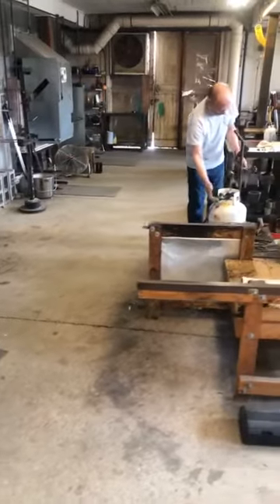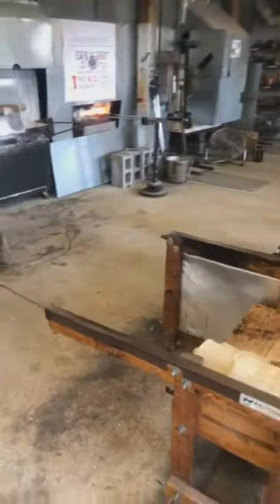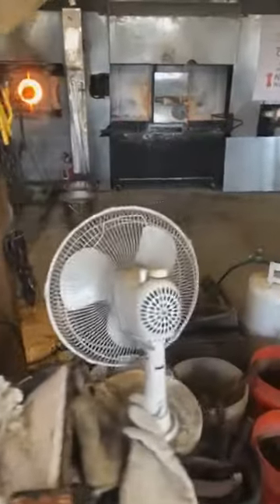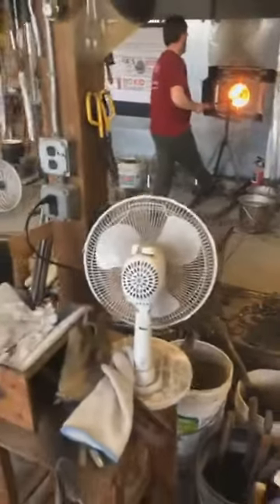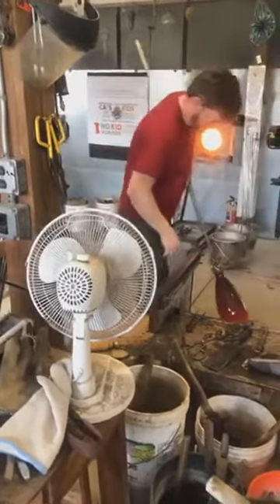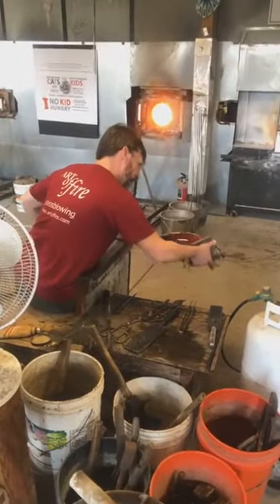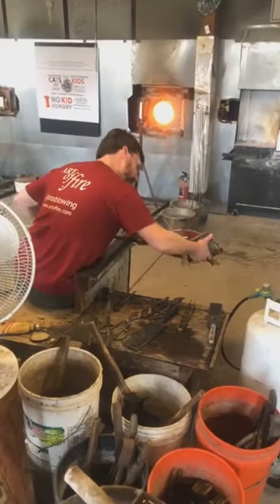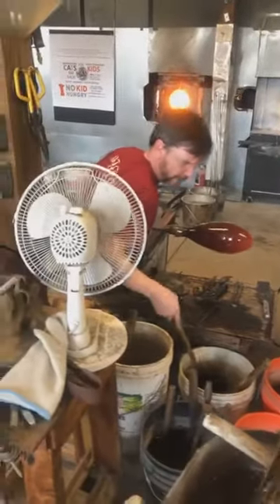What is it about the color that makes it stiff? The metal oxides, the chemicals that go into making it. The original glass batch is probably close to the same consistency and hardness, if you will. They're all the same coefficient of expansion, but with some of the glasses, because of the metal oxides that go into them, particularly if there are yellows, golds, reds, that sort of thing, they're very much different than the cobalt or even some of the copper that may go into them. So the different chemicals that go into the glass change its characteristics.